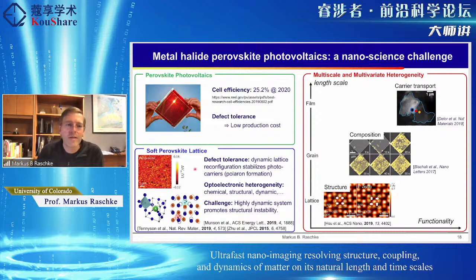And it was thought that this defect tolerance is a result of the following: after the photocarrier excitation, there is a dynamic lattice reconfiguration which stabilizes this photocarrier. And so instead of forming excitons, it is assumed that we are actually forming polarons, so that the electron and holes are isolated from each other and screened from this local lattice deformation. And so this polaron physics in perovskites is very poorly understood.